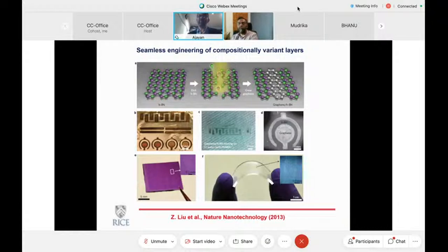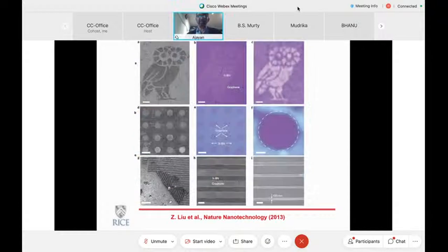And you can think about interesting devices. For example, you could put a graphene domain, like that image in the middle right, within a hexagonal boron nitride lattice, and that becomes really a nice antenna. It's a 2D antenna, basically. And if you also have a semiconducting domain, for example a BCN type of structure, then you could have metallic, insulating, and semiconducting domains all in a single atomically thin layer. You can start to think about fully functional devices based on these, all in two dimensions. So it's really a beautiful example of how nano engineering can be done within two dimensions. We have made many different patterns and engineered two-dimensional architectures using this approach of stitching together domains of isostructural materials.